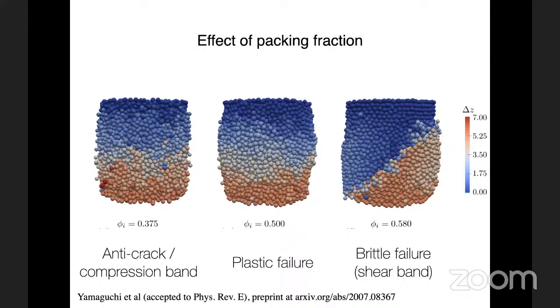It fails by a compressive failure, like a compression band, in the direction that they are compressing rather than a shear band. And one of the more intriguing things we find is with the same material parameters, the same physics, we can cleanly go between 3 different failure modes: a compressional failure, plastic failure at intermediate volume fractions, and a brittle failure by shear banding at high volume fractions.